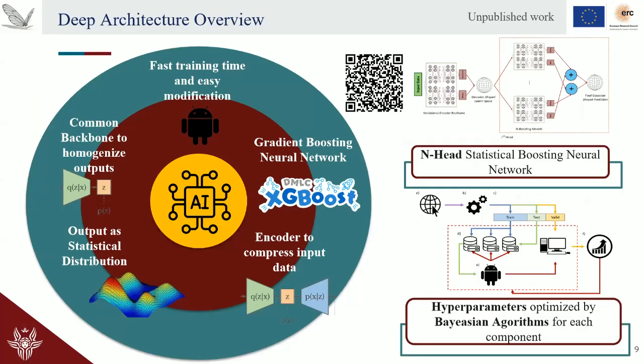Here we decided to treat the mechanical response not by modeling the whole stress-strain curve, but just by modeling some pivotal points, such as stiffness, yield, energy absorption, and the UTS of the material. In order to do so, we had to greatly improve the complexity of our AI model, since the task itself is very complex. We are dealing with both topology and print parameters. In this case, we had to use a multi-head statistical boosting neural network. It's a neural network by definition. It's multi-head, so it has one specialized head for each mechanical property that it's trying to predict.